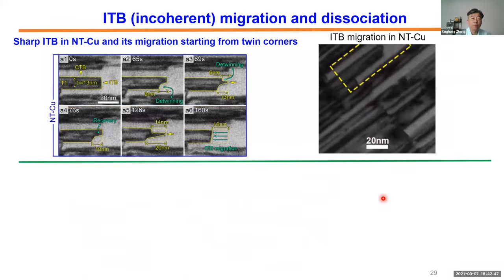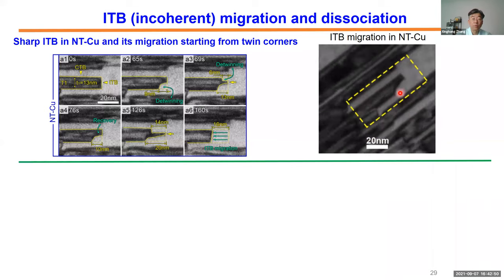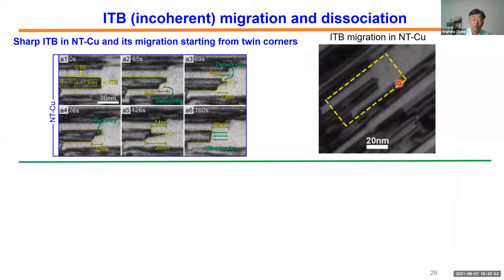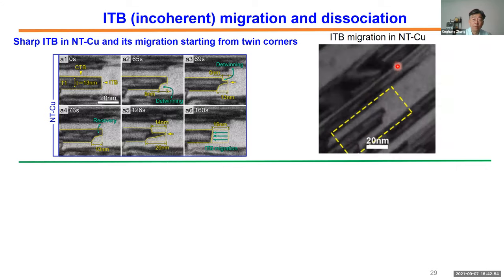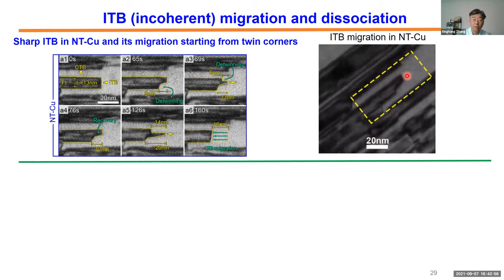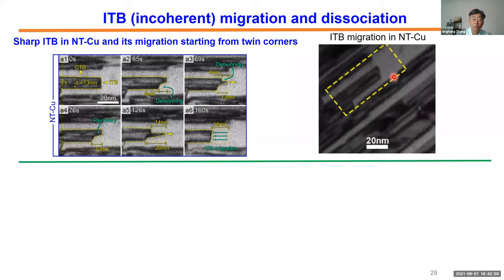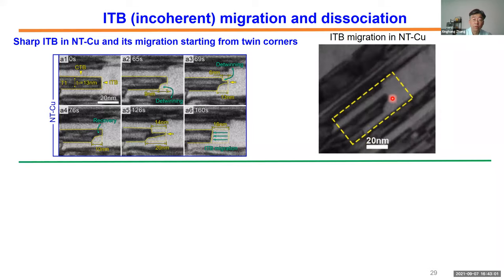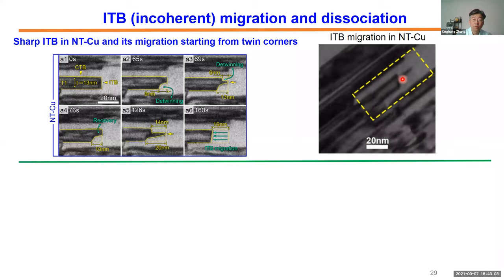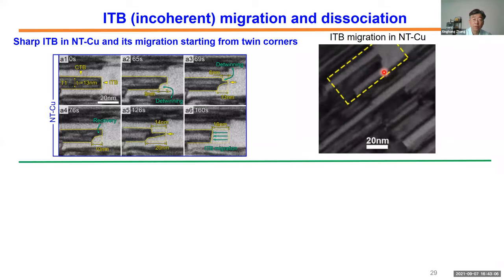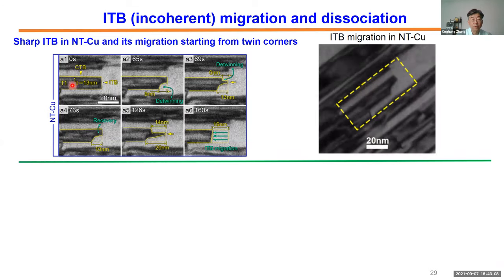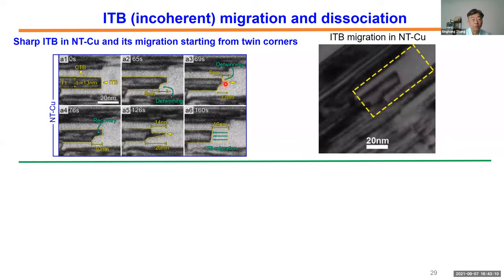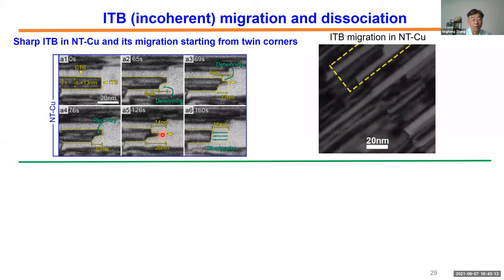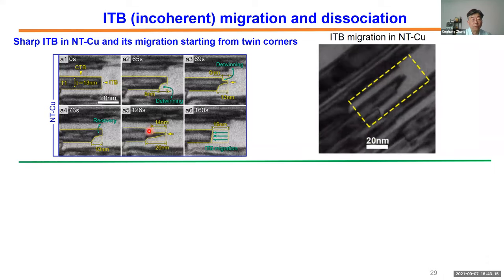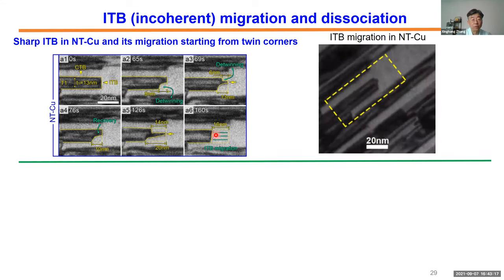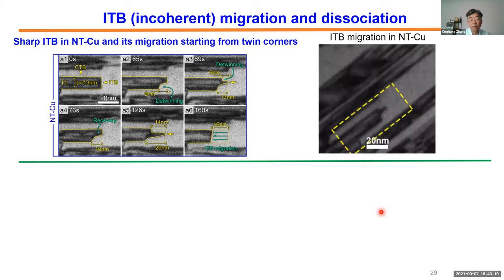So how do we explain the detwinning phenomena? This is detwinning in pure copper, nanotwinned copper. And this video plays repetitively a couple of times. So if you have a twin boundary, what happened is this twin boundary start detwinning from corner. And when detwinning from corner occurs, they leave a very sharp twin tips in the center. And so this snapshot shows us the formation of the twin tips. And the tips become really unstable. Then there's a drastic collapse of the twin tips. So then it leads to this detwinning event.